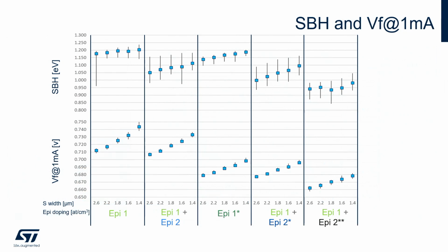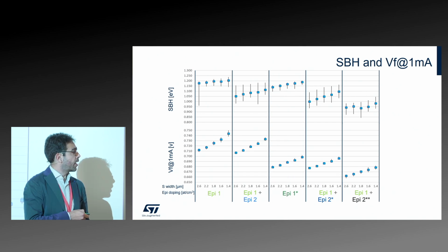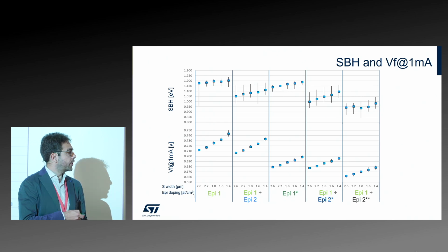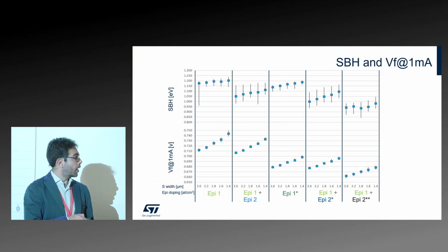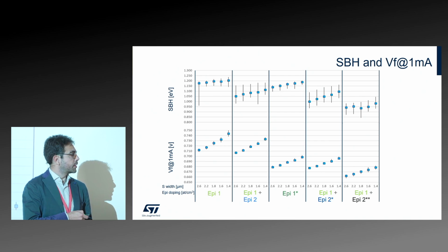The top part of the plot is the Schottky barrier height, here is the VF. Starting from the typical low doping, I can see that my pitch modulates the VF as expected, because I just have a lower Schottky area, so the VF increases. And as expected, the Schottky barrier height doesn't change because it depends on the surface. Again, if I put my stack epi 1 and epi 2, where epi 2 has a higher doping level than epi 1, the Schottky barrier height falls down as expected because of the higher doping, and I can modulate the VF. But you can see that VF doesn't feel the doping of the epi 2 so much. Basically, they are the same value. There is just a slight shift down, but it's the same value.